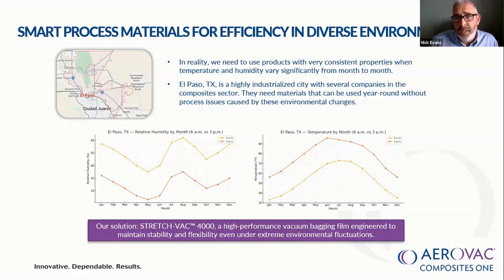Some people have the luxury of a temperature, humidity and dust controlled clean room. That isn't always the case, and high temperatures and low humidity conditions can really tend to dry out the film and make it feel crispy and brittle. So Aerovac took this on board and responded to our customers' request, and we developed STRETCH-VAC 4000 as a film to address some of these issues.